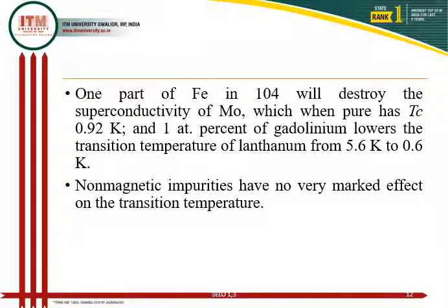Only one part of iron in 10^4 will destroy the superconductivity of molybdenum, which when pure has a TC of 0.92 K at 1 atmospheric pressure. 1 at. percent of gadolinium lowers the transition temperature of lanthanum from 5.6 K to 0.6 K. So this is very important. The presence of magnetic behavior, magnetic compounds, may reduce the temperature. However, non-magnetic impurities have no marked effect on transition temperature. These are a few conclusions that we have drawn based on experiments.